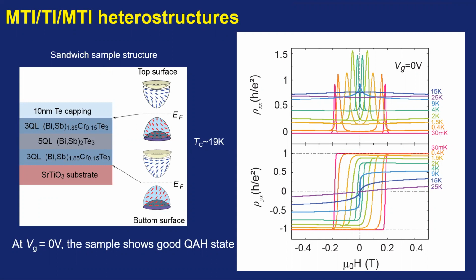But in this kind of structure, we use the same doping. We can see this is 3 quintuple layer bismuth antimony telluride, this is 5 quintuple layer, 3 quintuple, all chromium doping. This looks like a symmetric sample, and we carefully tune the bismuth antimony in each layer to tune the chemical potential in each layer to the charge neutral point. So this means that we can achieve the quantum anomalous Hall state at 0 gate voltage.